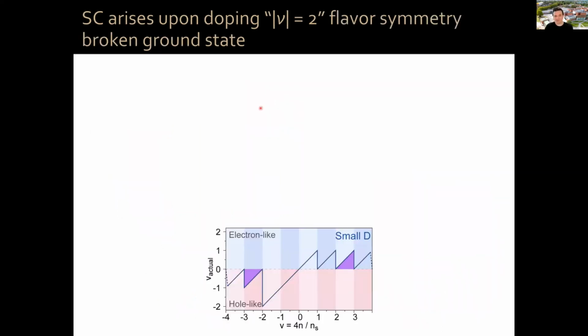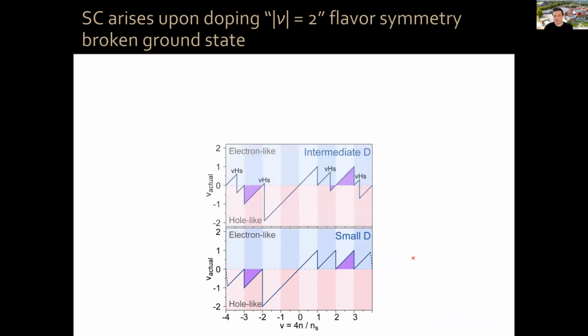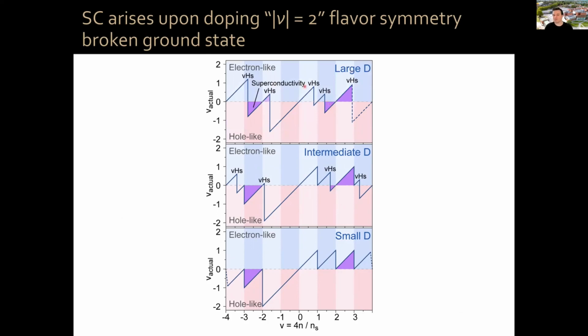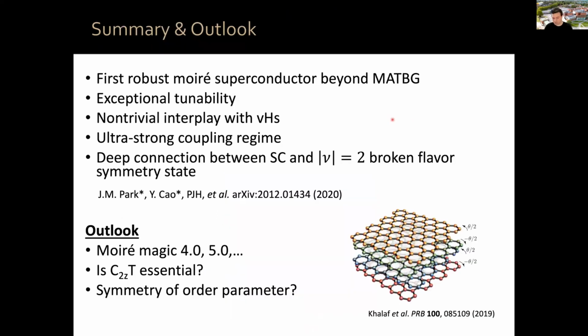Okay? So we can look at this schematically here. This is showing the filling factor, and here the actual filling of your flavors. You can see here the 2 Fermi surfaces which are filled. This purple means superconductivity. Now, as you increase the displacement field, your Van Hove singularity leads to a reset which is too strong. It actually leads into hole doping of your system. So you have 2 Fermi surfaces, but at an earlier filling factor, and then this thing becomes even stronger at larger displacement field. And we can see that in both regions of the phase diagram.